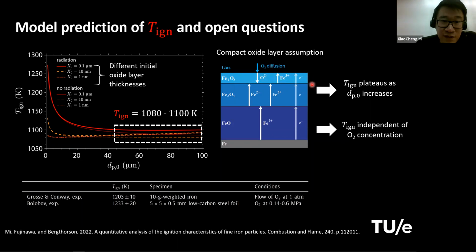But once this layer is formed, the interface between these layers is just at equilibrium, and the internal diffusion is completely driven by the gradient between these layers and the thickness of these layers. So the gas phase concentration, or the collision frequency of the gas phase molecules, is not really the rate limiting factor, right? It can become a rate limiting factor if the oxygen concentration is really low. According to the literature, it has to be lower than 10 to the minus 4 atmospheric pressure in terms of partial pressure to become rate limiting. That means for anything from normal air to 100% oxygen, the collision rate of the O2 molecules is way faster than the internal diffusion rate, so it does not become a depending factor.